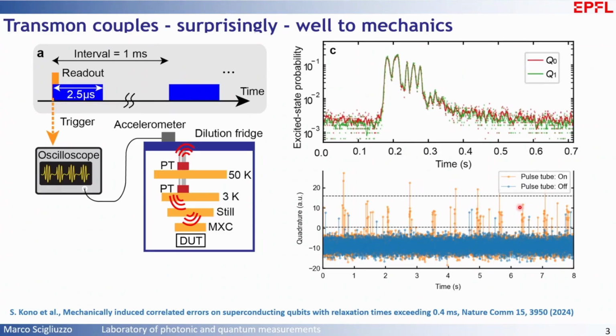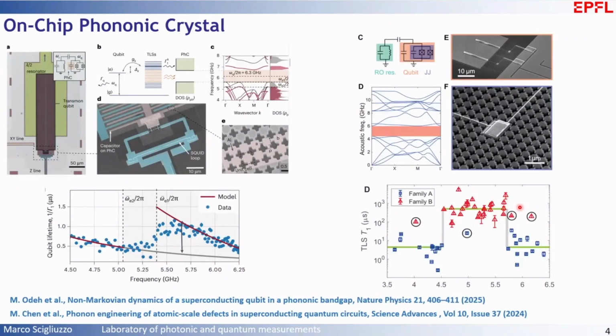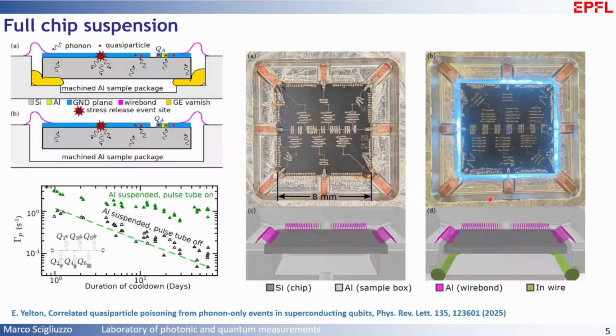People are, in fact, also aware of this, and there are many strategies already for isolating superconducting qubits from phonons. We can see that a transmon will increase its lifetime when it crosses the phononic bands. In a phononic crystal, the TLS made on the phononic crystal will increase their lifetime themselves. We saw that the quasi-particles have different dynamics with the pulse tube on and pulse tube off if they are isolated mechanically. So indeed, all the paths that I showed before are important and coupled to the mechanics.